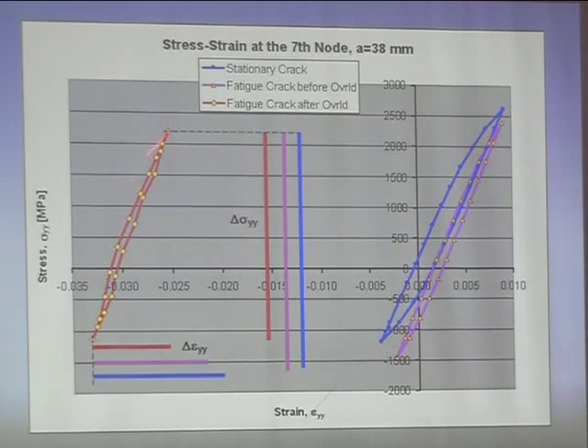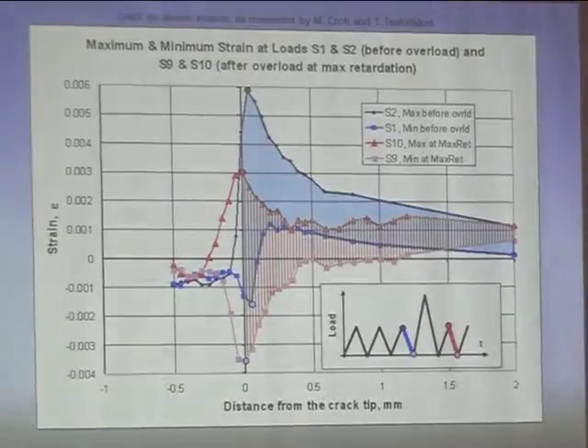After overload, the same cycle was causing almost no plasticity at all. We measured the same strain, but it was mostly elastic. The hysteresis loop was almost zero thickness. And I think that shows why the displacement didn't change, because it was hard. The plastic zone didn't have a chance to expand.